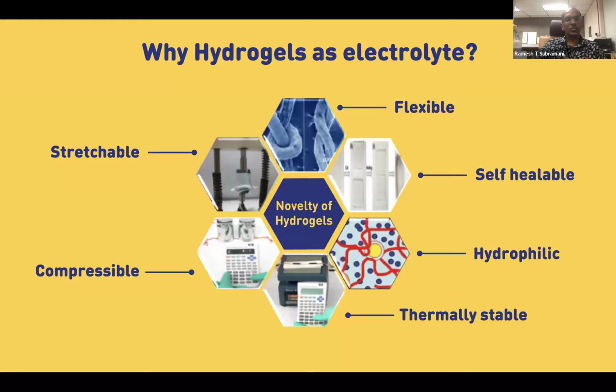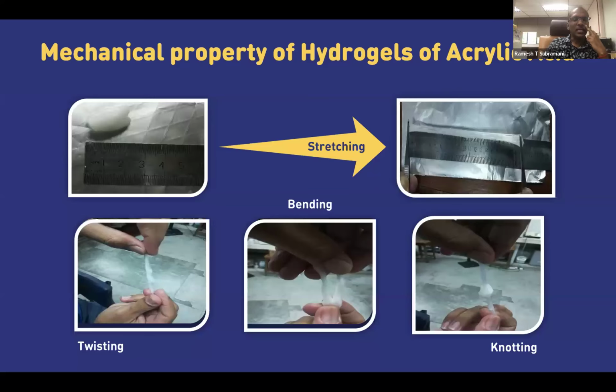And hydrogel electrolytes are highly stretchable, flexible, self-healable, hydrophilic, thermally stable, and also compressible. So here you can see a hydrogel of acrylic acid. You can see we can twist it, we can bend it, we can even do knotting, we can even stretch it more than 200%.